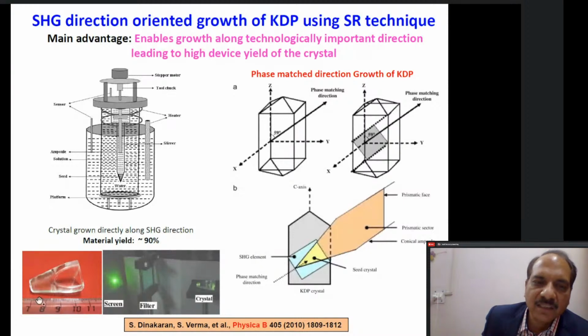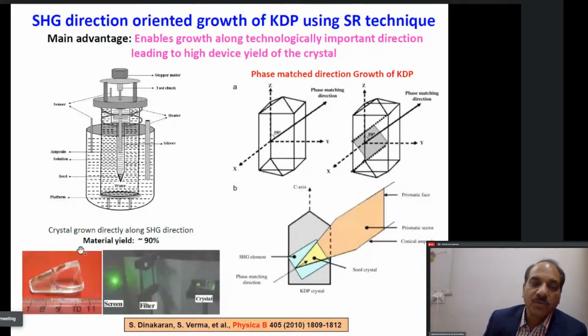When we cut this crystal, we put it in the laser beam path, and we were able to see the axis of this crystal. When the laser was passing through the center of this crystal, we were able to see the green. So second harmonic generation was generated, and we were really excited. We have proved it now. Only the bottom 5 mm was cut because we needed a flat surface, and a little bit from the top was cut. So only about 10% was lost. In fact, the usable material increased from 20 or 25% to 90%.